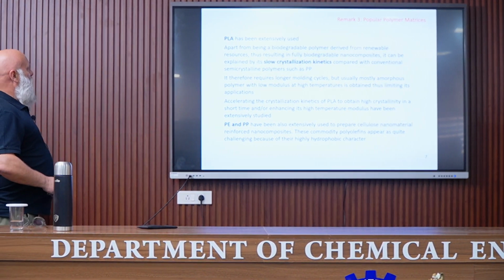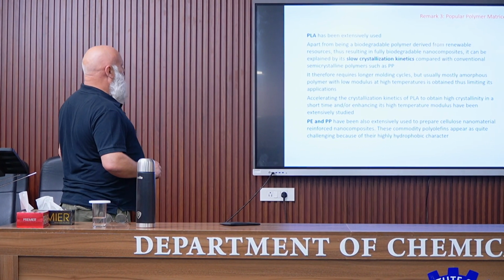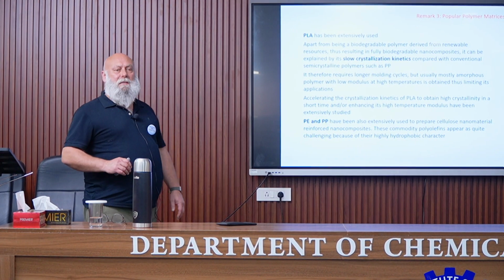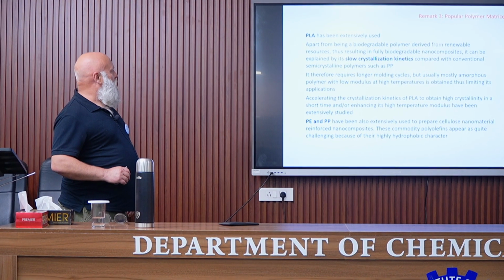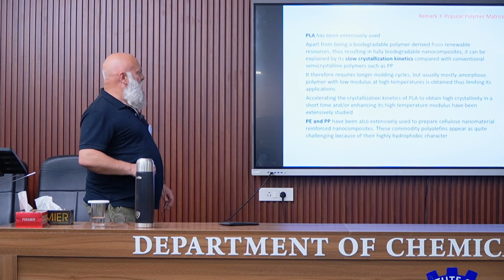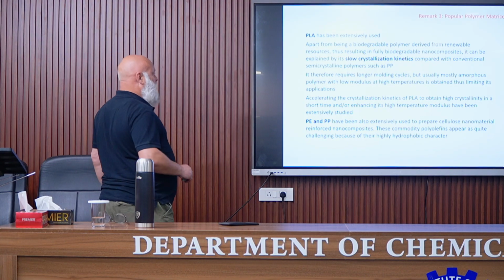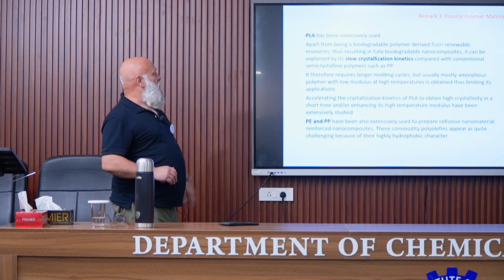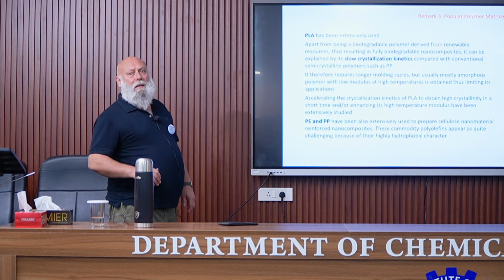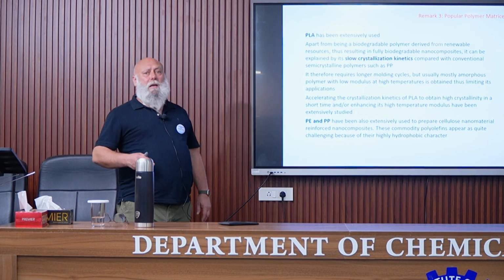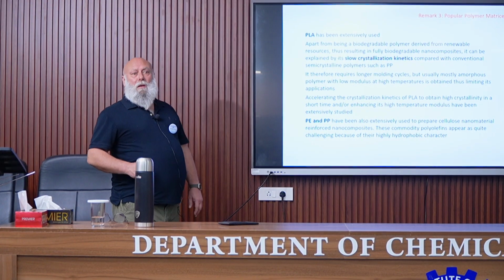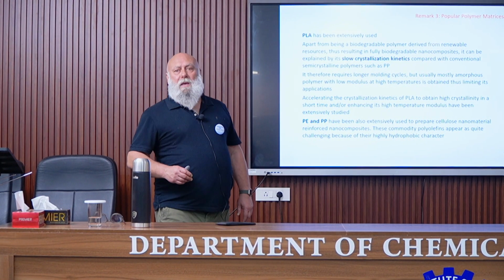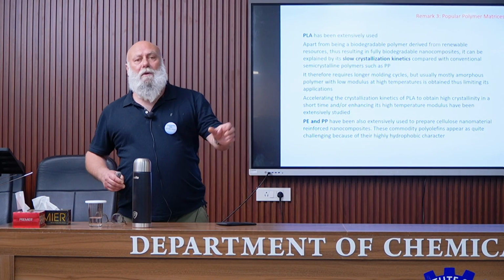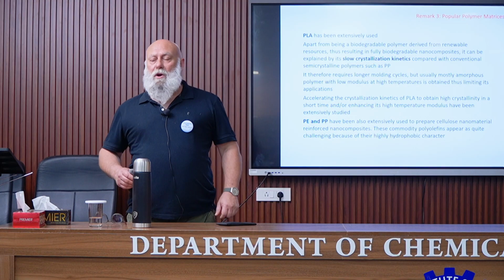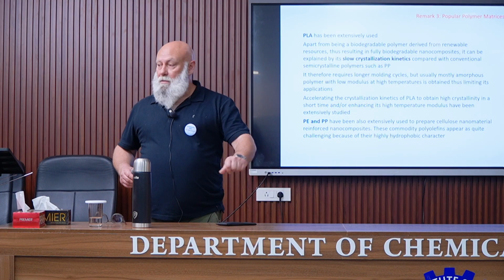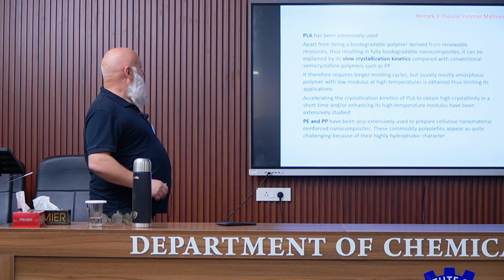Apart from being biodegradable and derived from renewable resources, the objective, of course, is to obtain fully biodegradable or compostable nanocomposites. The interest can be explained by the slow kinetics of crystallization of PLA compared to other polymers, meaning that it's necessary to use a longer molding cycle. Usually PLA is mostly amorphous with a low modulus at high temperature, and high temperature is not so high, it's above Tg, and remember that Tg is 60 degrees. At the beginning of the PLA story, people were thinking about coffee cups, and so you imagine the polymer with a Tg at 60 degrees, and you pour some hot water inside. It doesn't work very well.